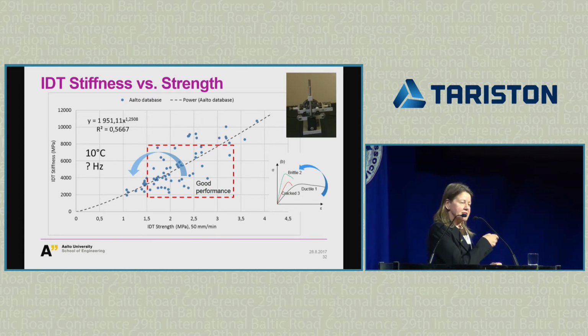Air voids drive this one, because air of course has no stiffness and no strength. So the air voids are driving here, while the stiffness is driven by the bitumen. And if you think of this idea from ductile to brittle, we are really going from here to here. Why I have this red box here is that I think some of these mixes, and this is actually proven from the research we did, are seeing something like this. It's not that you have a soft material there, but it's so stiff and cracked that it doesn't have any good strength anymore.